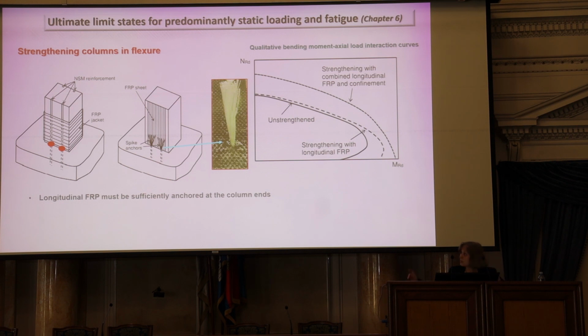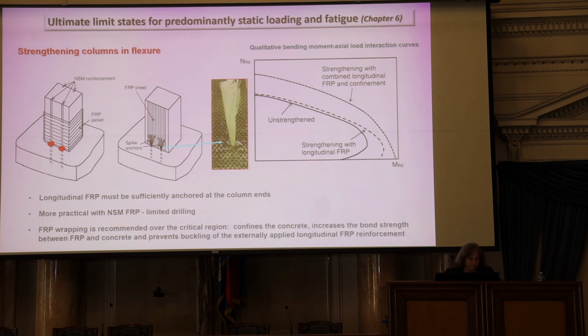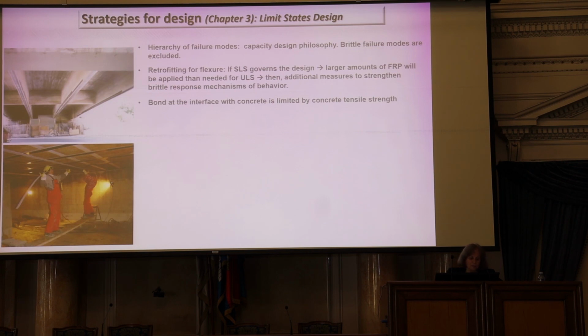So the locations that they show in red are the points where the FRP is expected to develop its peak strength. So more practical is, of course, to use near surface mounted FRPs. These require limited drilling, and of course always worry about the anchorage. In designing this, you need to worry about the hierarchy of the failure modes. You need to get rid of brittle modes of failure. A brittle mode of failure, for instance, is a shear failure. You need to increase the shear strength of your member to such a level that it will never be an issue before yielding or before reaching the flexural strength of its component.